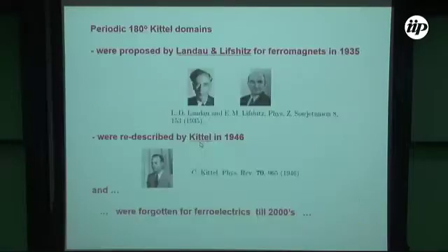Actually, they told this because they did not know the background physics that was done much before. And they were based on this depolarization field paradox. They just calculated the polarization field, as they discovered the things that Landau and Lifshitz told many years ago, and they told how really one should treat such a situation. So these are the famous 180-degree domains that were discovered by Landau and Lifshitz, and that are called in the literature Kittel domains, because Kittel published it in '46.